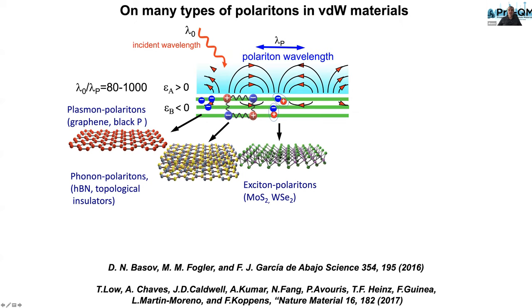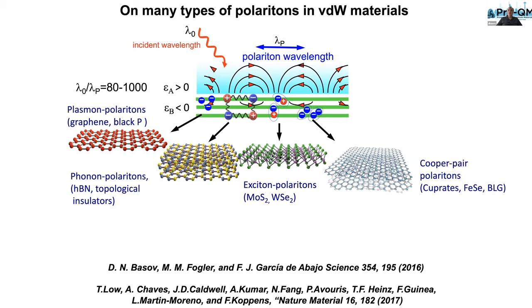If you are interested in semiconductor physics, you can try to form exciton polaritons, and I think this community is particularly excited about opportunities with exciton polaritons in more conventional semiconductors, but they're also supported by van der Waals solids that offer a variety of semiconducting substances. My favorite polaritons are actually Cooper pair plasmon polaritons. And here the origin of the negative dielectric function comes from superfluid density. I like these polaritons because they are lossless. They are fundamentally lossless because the superconducting condensate is lossless. At least in principle, this form of plasmon polaritons could travel over infinitely long distances on the surface of superconductors.